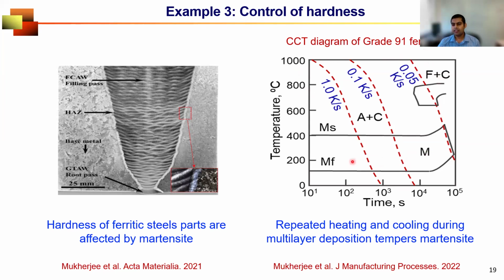This is a famous transformation diagram. And you can see that martensite forms for this particular material at a very low cooling rate, 0.05 Kelvin per second. And in additive manufacturing, what is the cooling rate? It's like 10 to the power 3 to 10 to the power 5 Kelvin per second, depending on the processing conditions. So it is guaranteed that whenever you process this material using additive manufacturing, you will end up having martensite. And this martensite will control the hardness of the part. But there is a small catch.